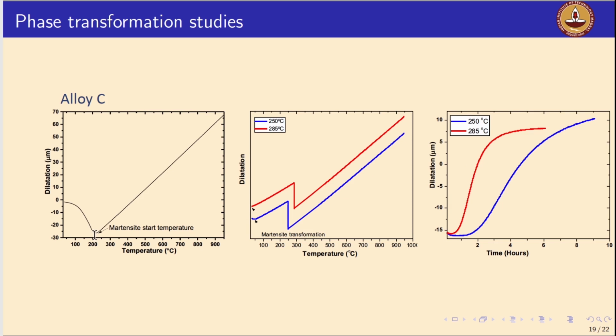And alloy C, again, is also a nice chemistry. If you look at it over here, we have the MS temperature we predicted, and we kept it at these isothermal bainitic holding temperatures. In a couple of cases we found very little or no martensite transformation from the dilatation. But for this chemistry, the actual time of bainite transformation is extremely high. For example, at 250 degrees centigrade, we'll have to hold it for close to 8 hours in order to complete the transformation, right? So that is not an ideal case, isn't it? We cannot hold it for 8 hours between passes or after welding, but without holding, we cannot complete the bainite transformation.